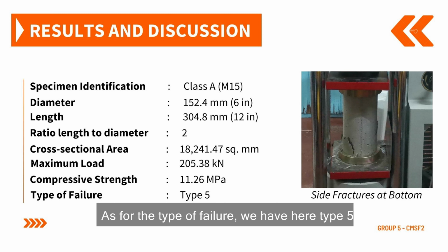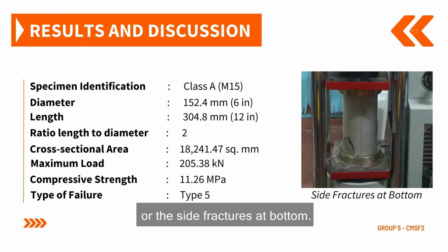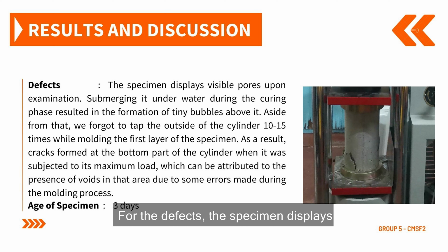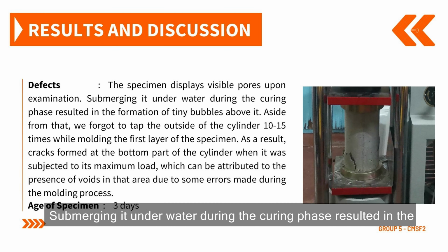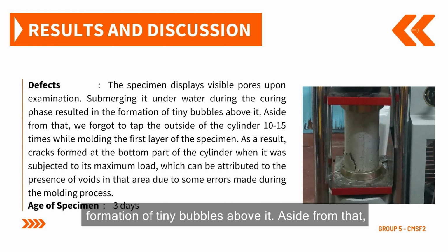As for the type of failure, we have here type 5 or the side fractures at bottom. For the defects, the specimen displays visible pores upon examination. Submerging it underwater during the curing phase resulted in the formation of tiny bubbles above it.